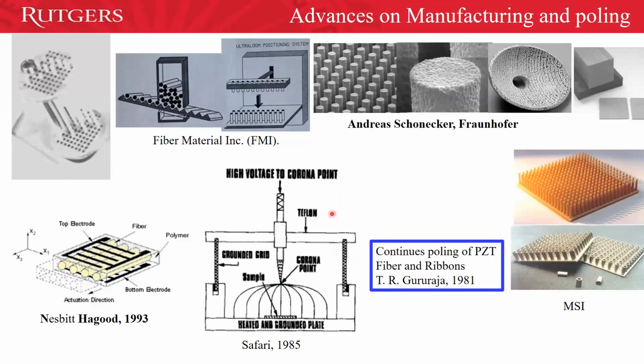When I was at MRL, I proposed applying PVDF work to polarize composites and ceramic. Later, when we came to Rutgers, we processed and optimized this corona poling process for continuous poling of composites. Very intelligent Nesbitt Hagood from MIT mechanical engineering proposed a finger type electrode and poling them horizontally in this geometry. So this became really a way of working with large area fiber composites.